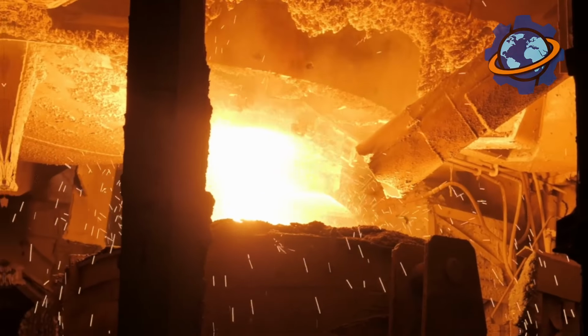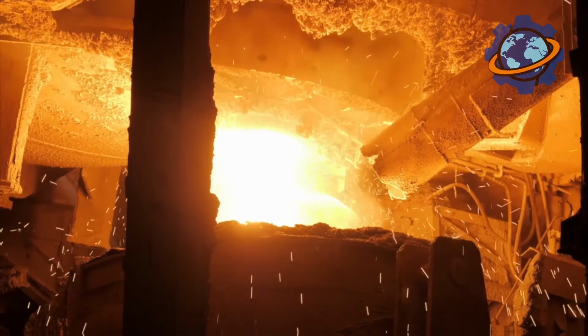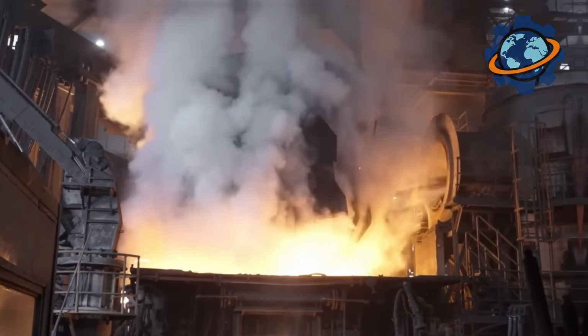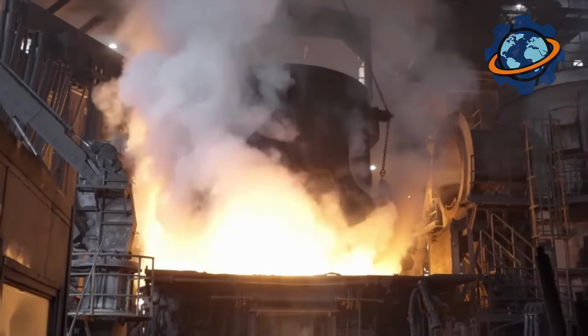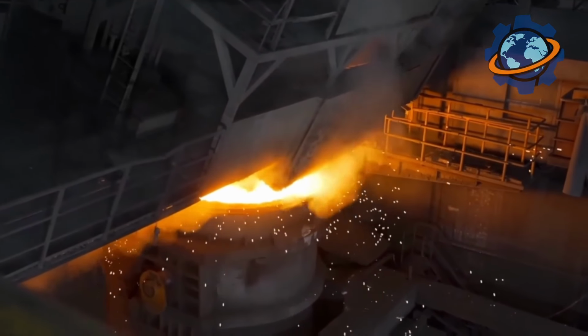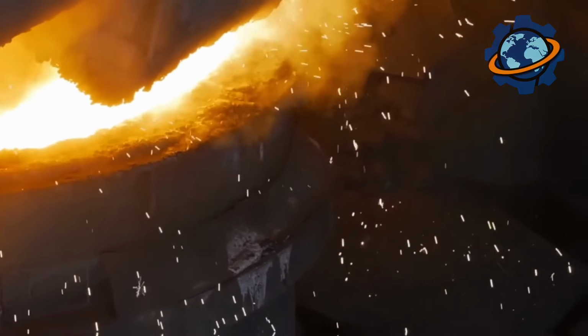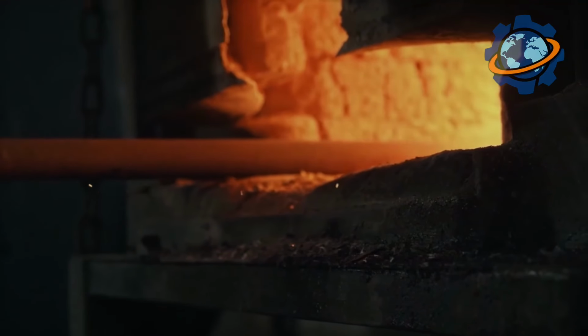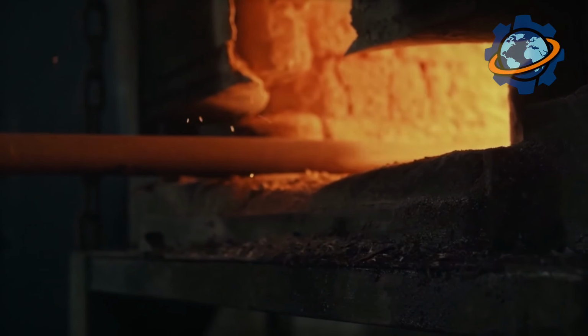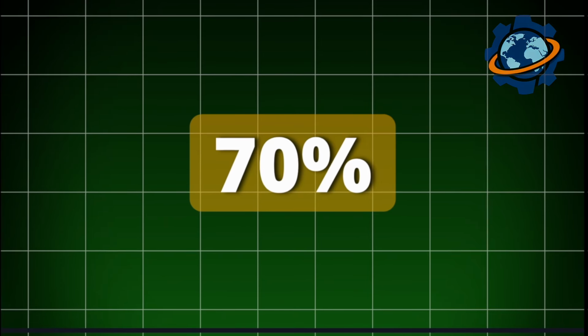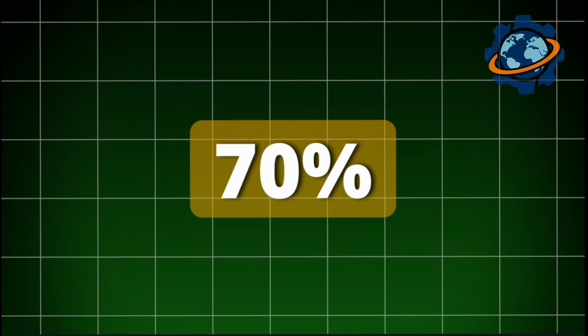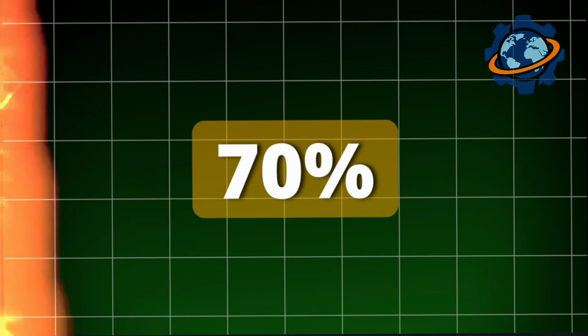You can't melt carbon fiber like aluminum. Heating destroys the crystalline structure that provides strength. Current recycling uses pyrolysis, heating composites to 1,000 degrees in oxygen-free environments, burning away resin while preserving fibers. Recovered fibers retain 70% of original strength, creating secondary markets. From plastic thread to aerospace revolution, the cycle completes.